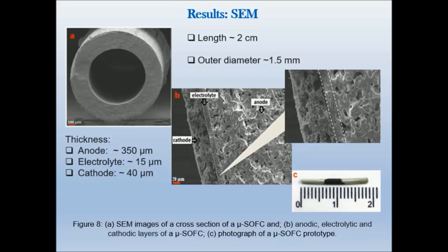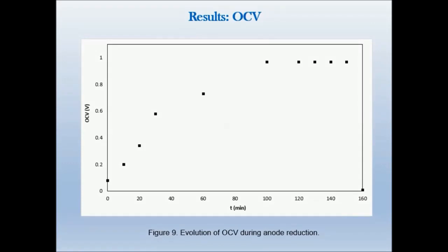It is important to mention that after the thermal treatment for curing the sealant, air or nitrogen is passed through the prototypes and the flow is measured before and after the samples to ensure that the sealant has no leaks. Then, reduction of the anode is carried out. The open circuit voltage values of the prototype during reduction are shown in this figure. It is important to mention that when there are small leaks of hydrogen, the OCV value does not approximate 1 volt. As anode reduction happens, OCV is gradually increased.